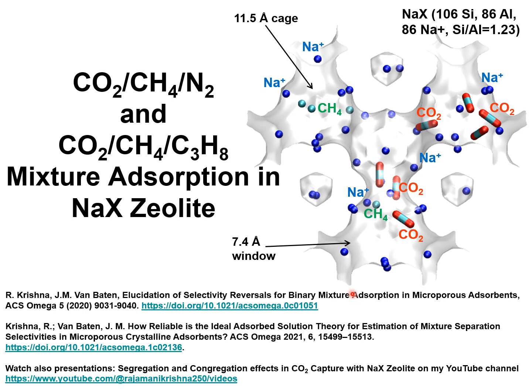A large number of experimental investigations and molecular simulations have demonstrated that adsorption of mixtures such as carbon dioxide and methane, carbon dioxide and nitrogen, carbon dioxide and propane in 13X zeolite exhibits strong thermodynamic non-idealities, and mixture adsorption equilibrium is not adequately described by the ideal adsorbed solution theory.